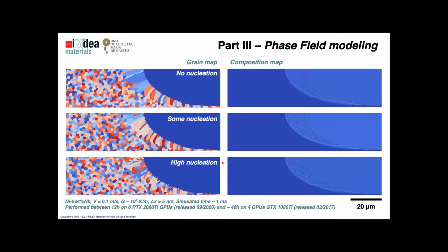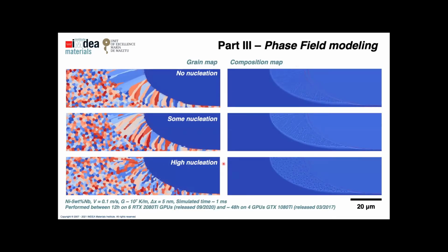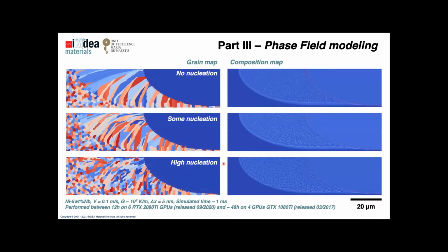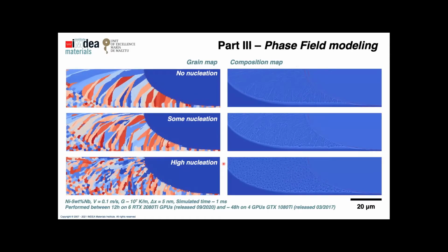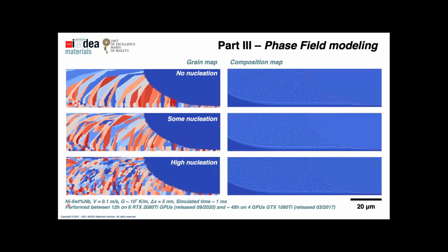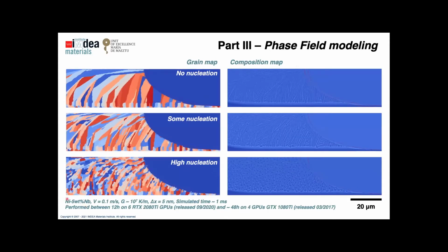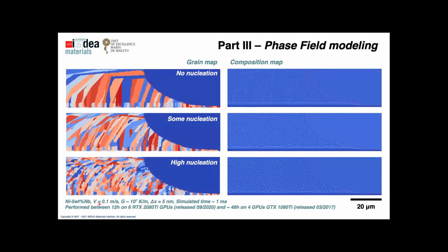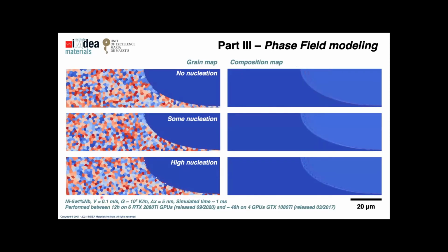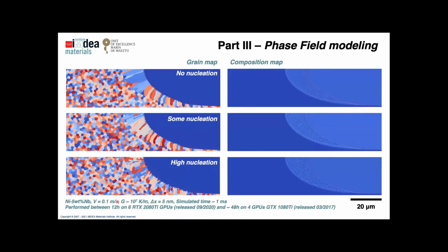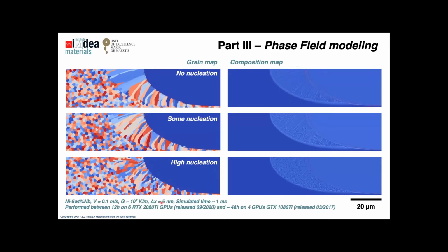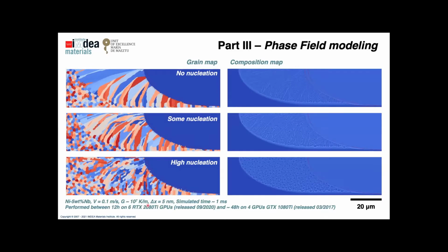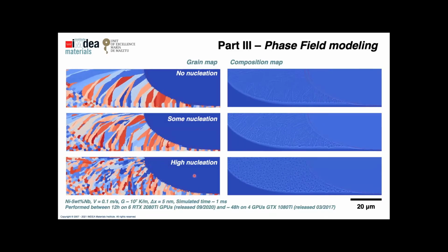So at this point, they're mostly cartoon illustrations of where we want to get. They're not yet completely at scale, even though they're using a reasonable binary proxy for Inconel, with velocities that are starting to be in the right range, even though we're also exploring larger ones. And pay attention, 5 nanometers is the scale that we need for the grid.